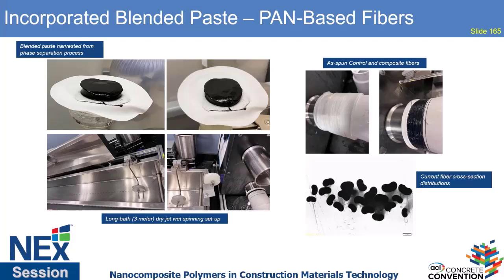We have a coagulation bath that we can change the length of to ensure we have good coagulation. These are some control fibers. These are some composite fibers as spun before any drawing or heat treatment. And this is a typical cross-sectional shape. And these aren't great fibers. I show this cross-section because you want a round fiber. These are actually bean-shaped, which means that we haven't optimized coagulation and gelation yet. And I wanted to show that because we're still seeing the property gain, which is great.